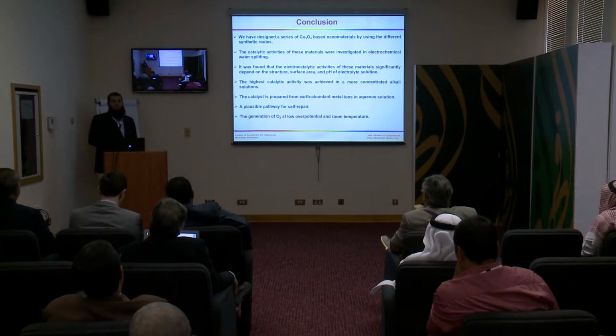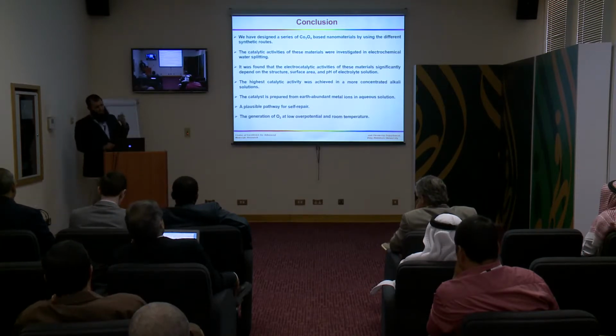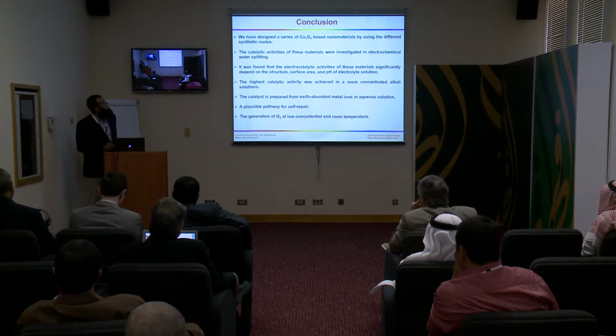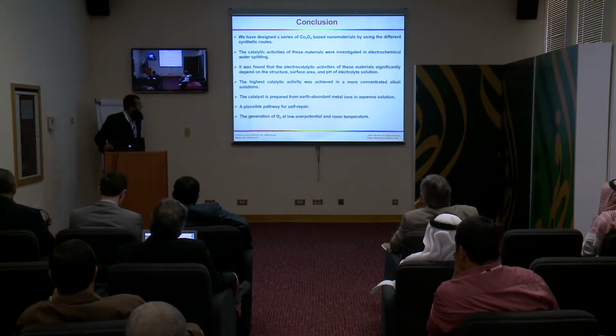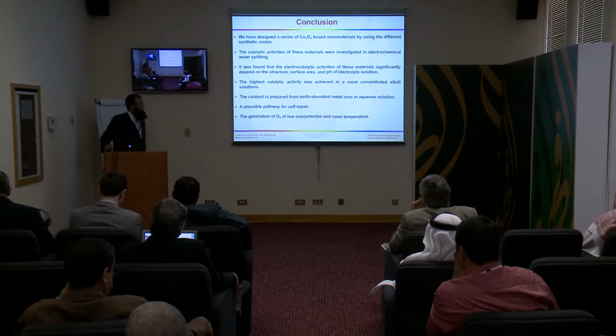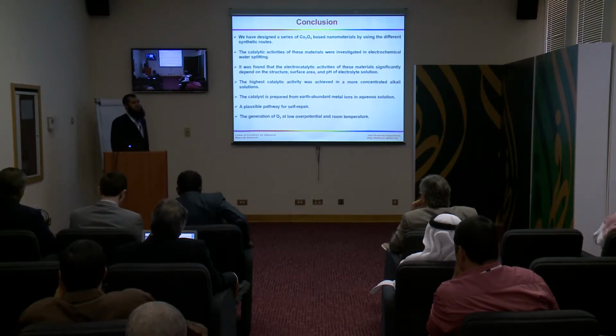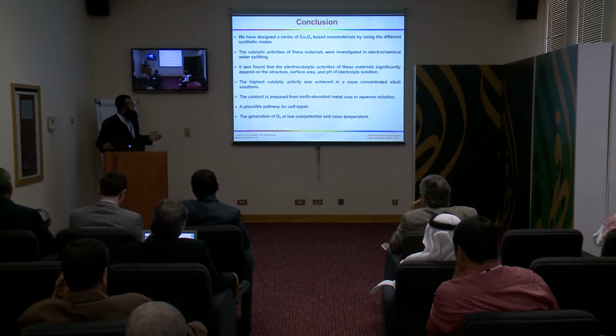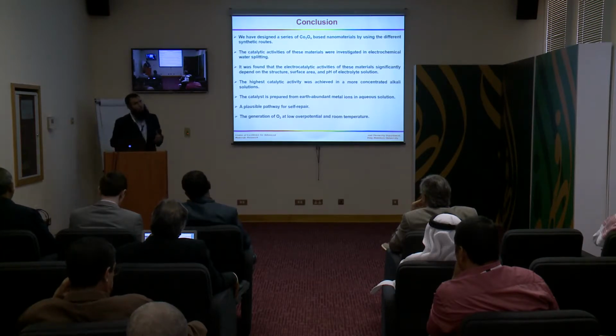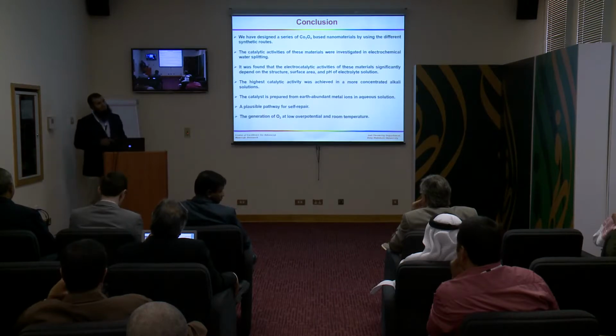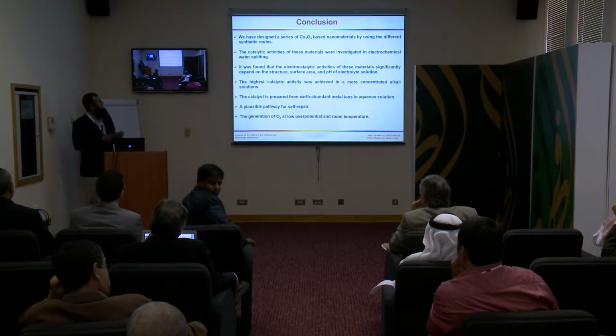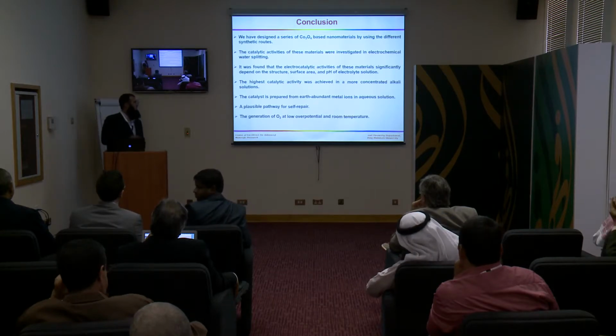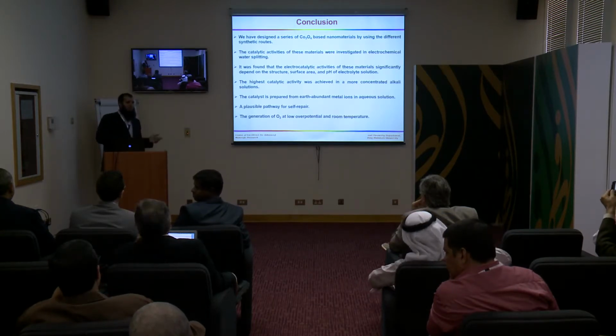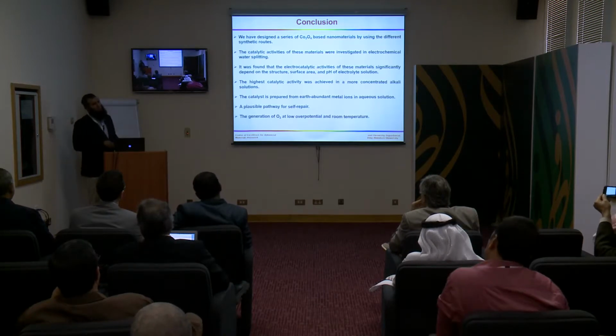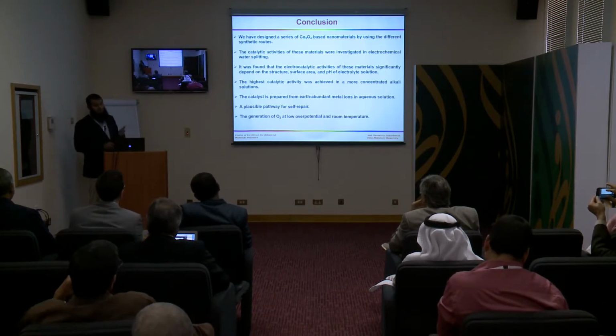In conclusion, we have designed different materials in order to check their role as electrocatalysts for water splitting, and we have found that cobalt oxide works very well as an electrocatalyst, but you have to design it in a different way. There is several literature showing that if you dope with some other element, it shows high performance, and we tried to dope with different materials. Till now we haven't achieved much, but as a mesoporous material, it shows high current density even at lower potential. Thank you so much.